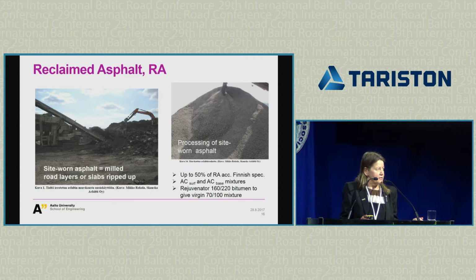So then we have this regular asphalt recycling. Site-worn asphalt is processed at asphalt plants and used in the surface mixes. Finnish specification allows using 50% in surface and base mixes. And then there's this rejuvenation agent like soft asphalt.